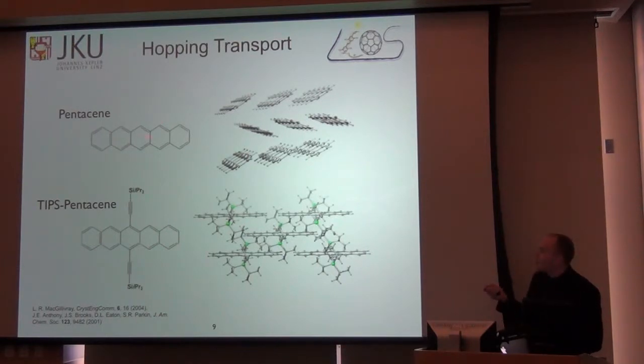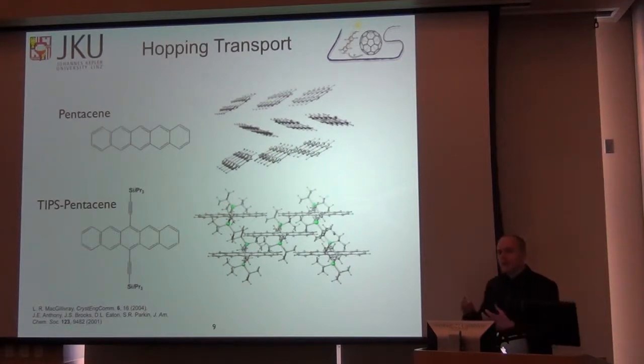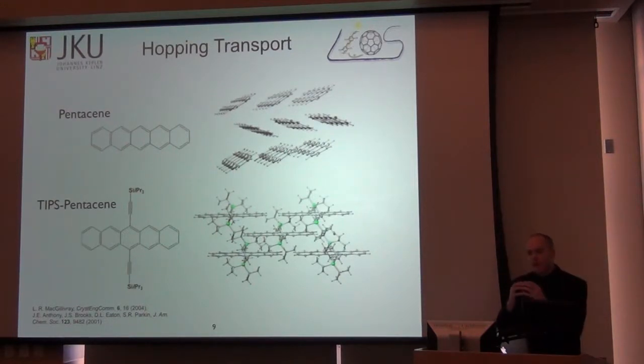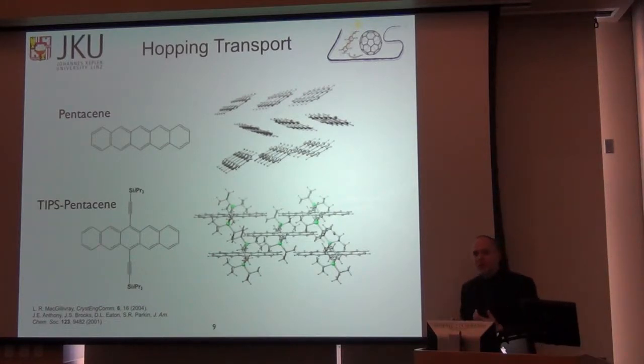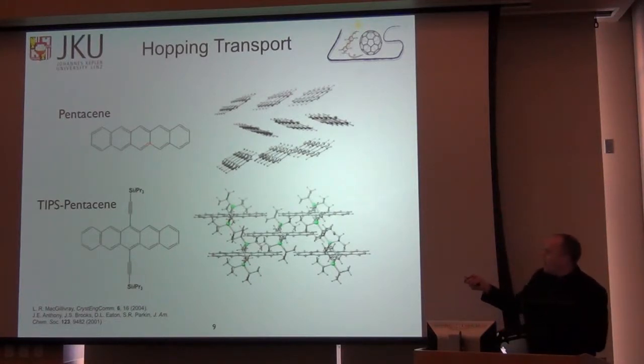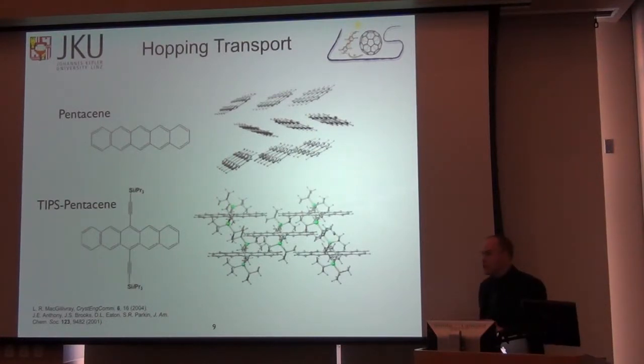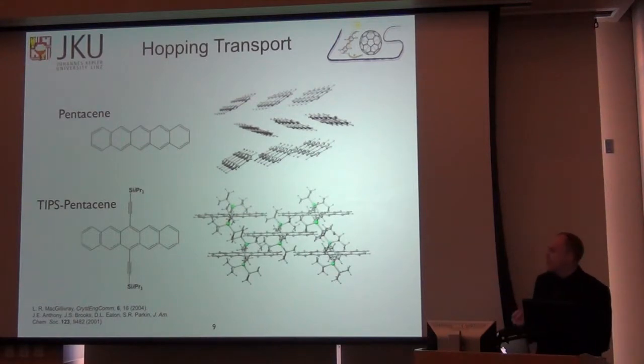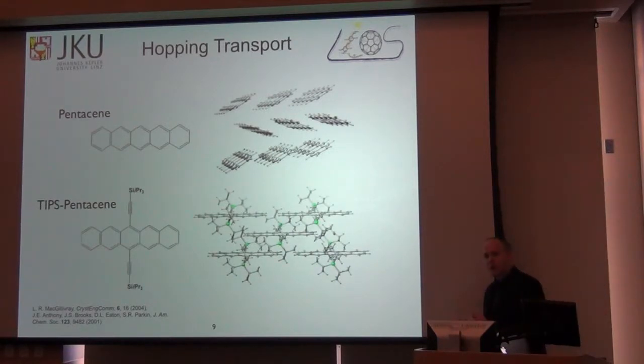So you have hopping from one molecule to the other. You can imagine that these molecules pack nicely, but at some point there's a grain boundary, and you have hopping across those grain boundaries. So whether it's intracrystallite hopping or intercrystallite hopping, the limiting transport mechanisms are definitely not on the single molecule, but hopping from one molecule to the other. So you have a semiconductor here, or a material that behaves like a semiconductor, but the optical properties are derived largely from the molecular structure, while the electrical hopping and transport properties are derived from the crystal packing in general.